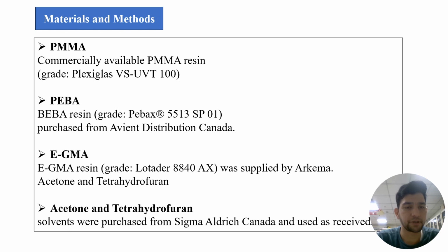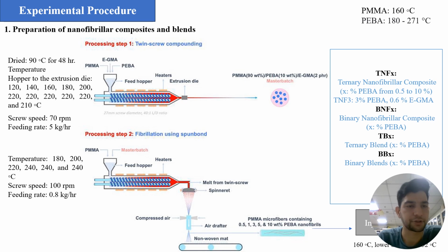Materials and method. The materials used in this paper are PMMA, PEBA, EGMA, acetone and tetrahydrofuran. Experimental procedure. The experimental procedure is a very interesting part of this paper, very good. So, preparation of nanofibrils composite and blend. In the processing step, in the first step he used twin screw compounding. This is the twin screw extruder, having a hole here, with a 24 millimeter screw.